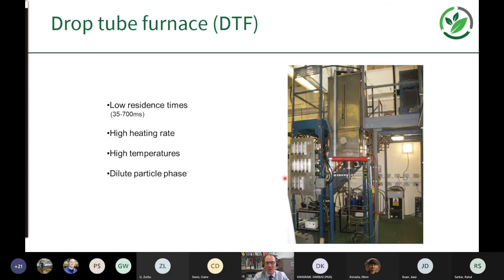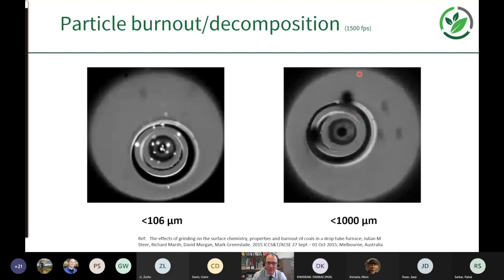So I've been using a drop tube furnace, and we use that to mimic this raceway region, this balloon-like bubble that's formed in the bottom of the furnace when you inject coals. And this gives characteristics which are similar to that raceway region: high heating rate, low residence times, high temperatures. And then these images are looking into this furnace and just illustrating that coal particulates, when they're injected in at high temperature, behave differently.